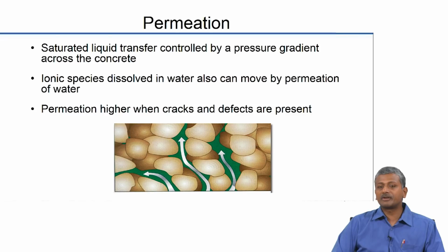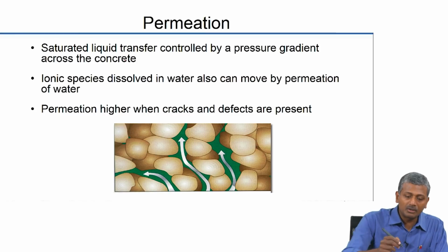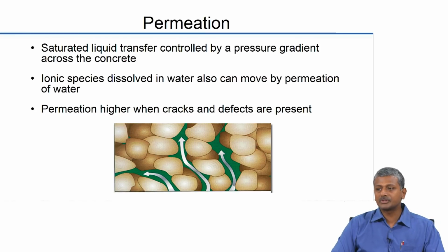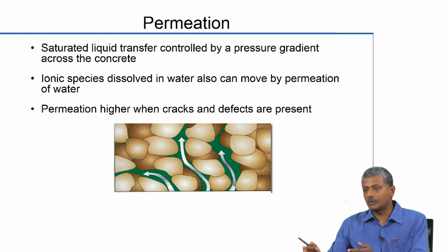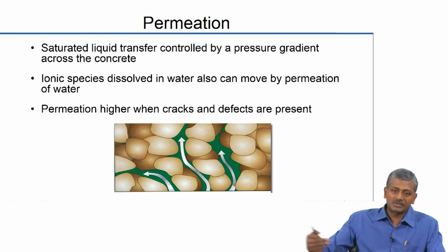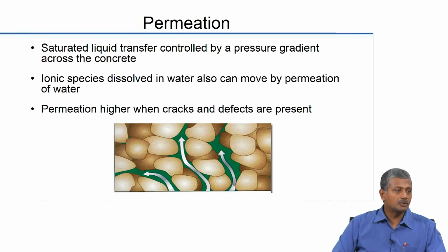The other major transport mechanism that occurs in concrete is permeation. Now, permeation or permeability is associated with the flow under a hydraulic gradient, a pressure gradient. So, saturated liquid transfer happens, which is controlled by a pressure gradient across the concrete. So, if you have high pressure of water on the outside, low pressure on the inside, obviously it will drive the water into the concrete.